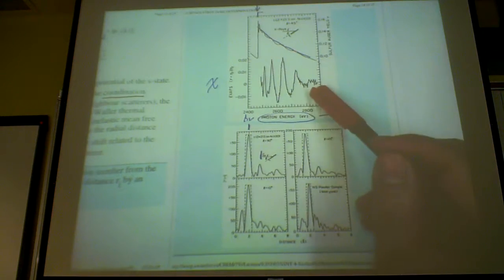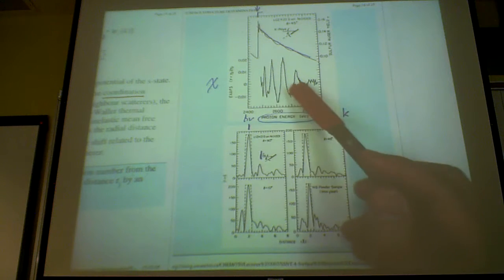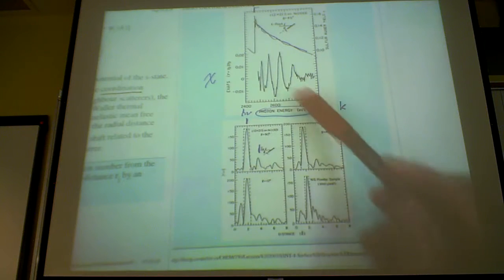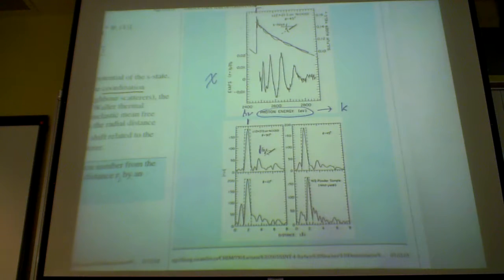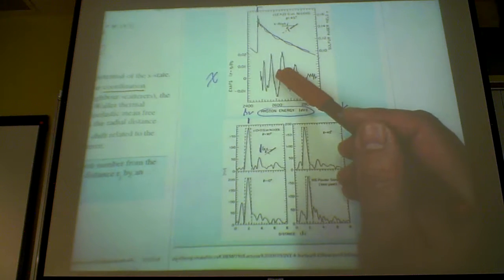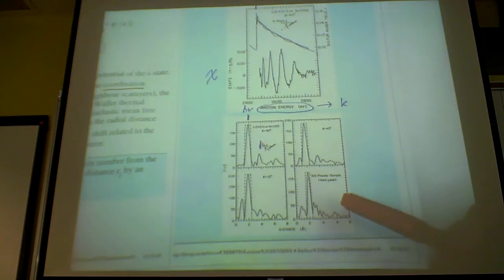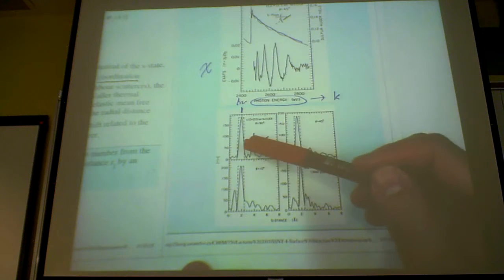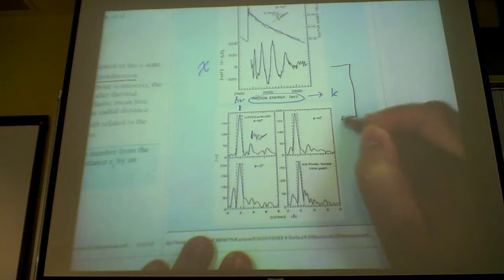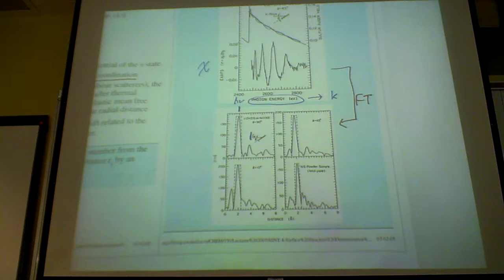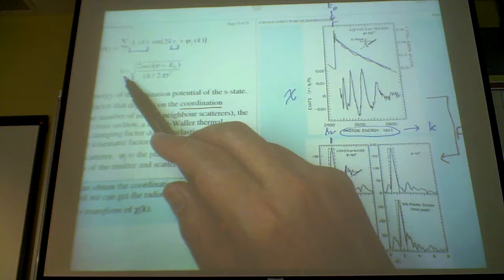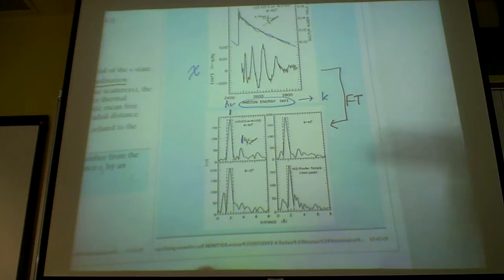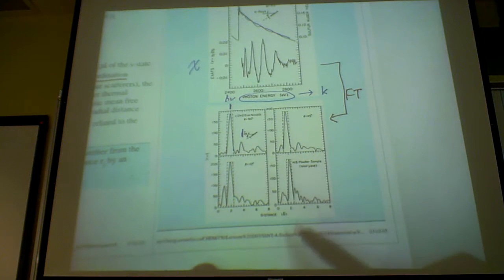All you have to do is to do a Fourier transform, in fact, a Fourier transform of this spacing. And when they do a Fourier transform of this spectrum, you can think of this as a power spectrum. Because whenever you get a power spectrum, you can get back to frequency domain. So you can either think of it as a frequency domain or a power spectrum, depending on how you treat this. So you convert this by a Fourier transform. So you go from here to here, you do an FT, Fourier transform. And what you find is that you find peaks. So you have photon energy, which is K-space. This is the wave vector space, which is inverse distance. You do a Fourier transform, so you get distance back. So you get R back. That's the interatomic distance that you've got.